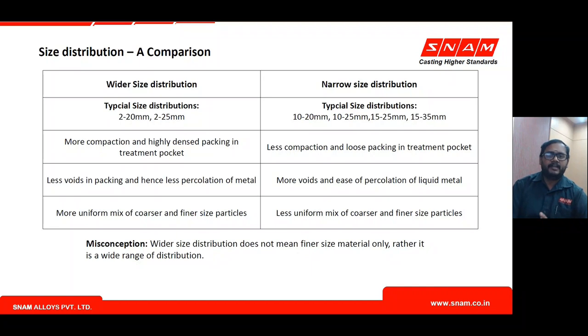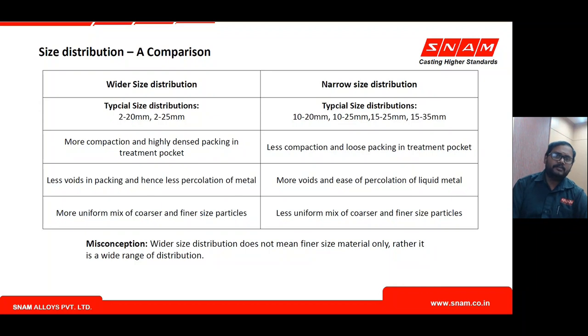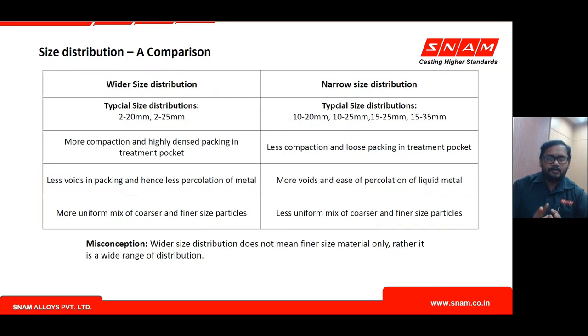With compacted packing, liquid metal finds it difficult to percolate into the packed alloy. When it does percolate, the finer material dissolves first, which locally increases viscosity of the metal since this is a ferro silicon alloy. As local viscosity increases, fluidity decreases and percolating capacity falls. This effectively delays the reaction and dissolution — the delay is desired so that the reaction happens only after the treatment ladle is fully filled.